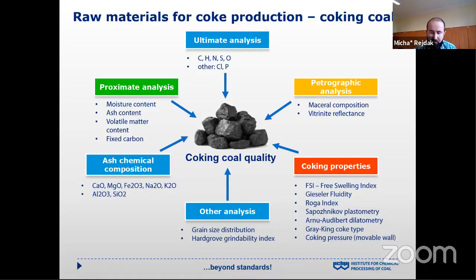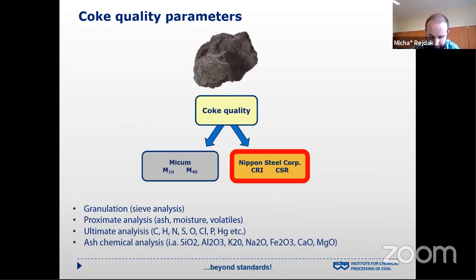The Sapozhnikov test was developed by Russian researchers, and we can use it to determine the plastic layer thickness of coking coal and contraction indices. In general, coal blending procedures for coke production are based on a combination of rheologic and petrographic parameters for individual coal samples, which can be used to select coals to make up a blend with specific coking properties.